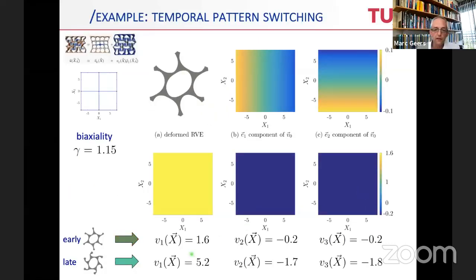So this is typically what comes out. You see that I show here the magnitudes of the different fields. On the top right, you get the standard slow displacement field, the mean field displacement, the one component and the two components. That's standard. I think more interesting are the three at the bottom here, which are the amplitudes of the different modes, so the V1, V2, and V3, which respectively correspond with the patterns that we've seen earlier. So a pattern is in fact a linear combination of modes. So you'll always see a contribution of V1. This is actually the dominant one. This is the one that is shown here, which is constant in this case for this infinite periodic stacking. Later on, the V1 amplitude will become larger and the V3 one will become more negative, and so will the V2 one, which picks up this later pattern 3 prime.